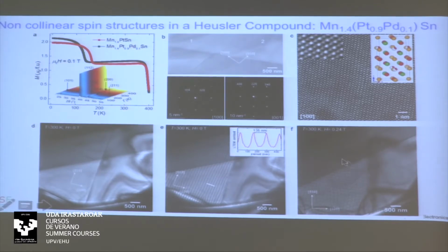Here is a conventional bright field transmission electron micrograph where you can see all the atoms, and we can see that we have a beautiful lattice. And then what you can see in the Lorentz mode are these black and white stripes. These correspond to a helical phase, not a skyrmionic phase, where the magnetization is rotating from one direction to another, so we see the in-plane component of magnetization change from black to white, and that's what we're detecting in this Lorentz mode.